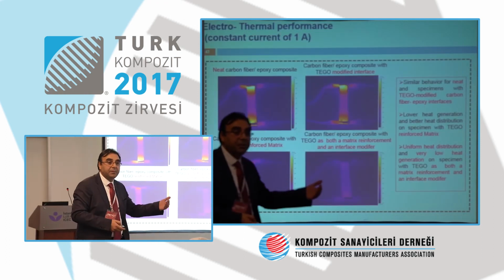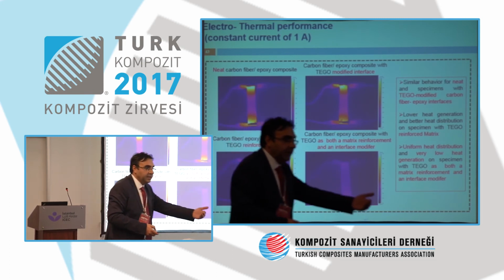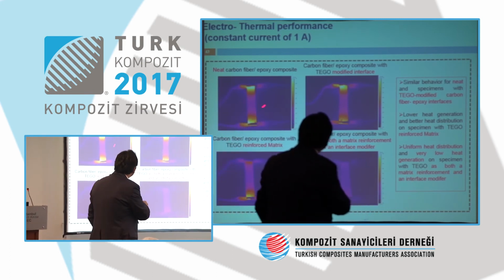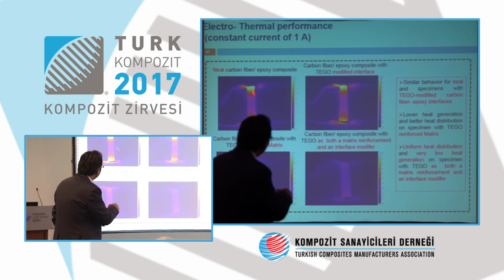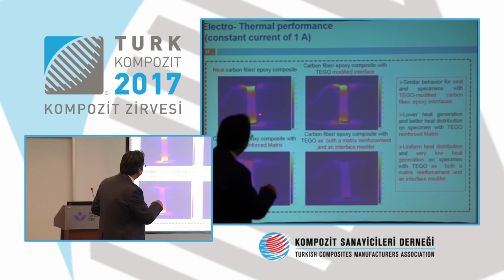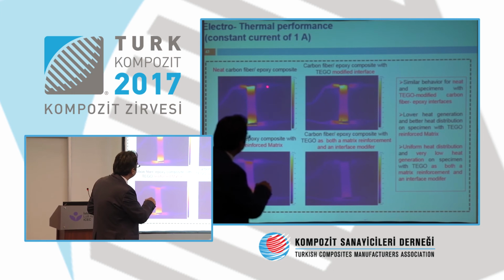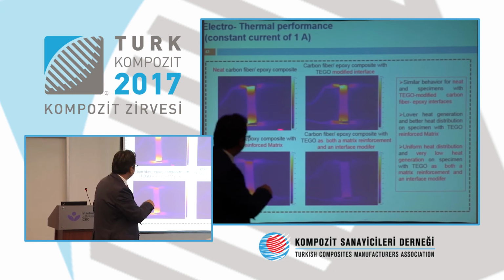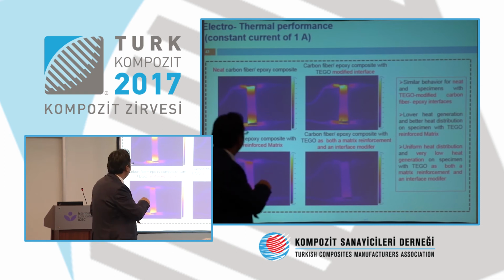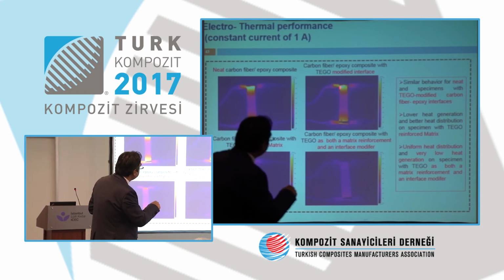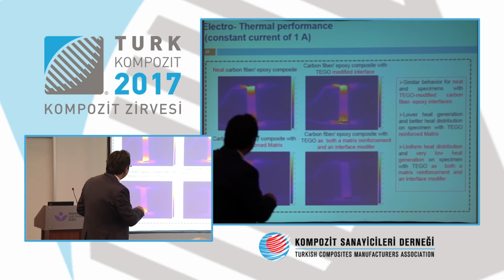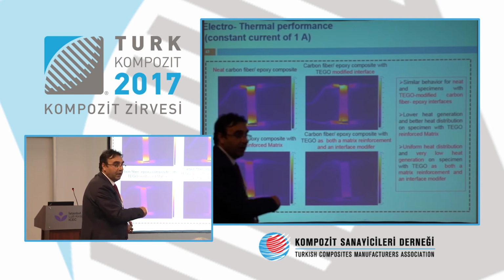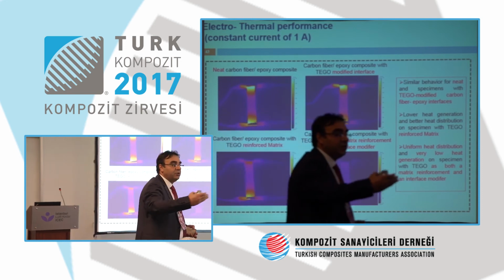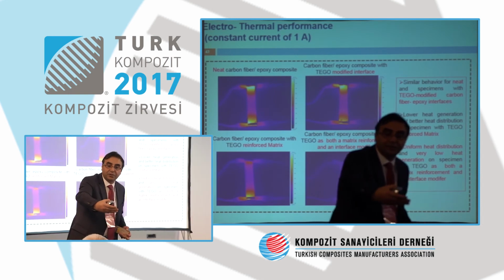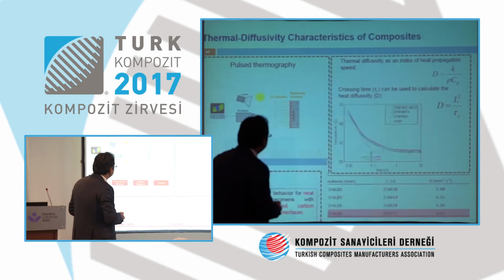And we look by thermography at whether these are the cases. This is the thermography image of our material, and you see that this is not conductive. Then if you put the crocodile clips here, you have a lot of heat generation because the current doesn't want to pass through it. And this is interface modified. Again, you have a similar problem. If you have a matrix, it's a little bit better than that. But if you have both, then it gives you a pathway so that you can conduct the electricity. Why is this critical?